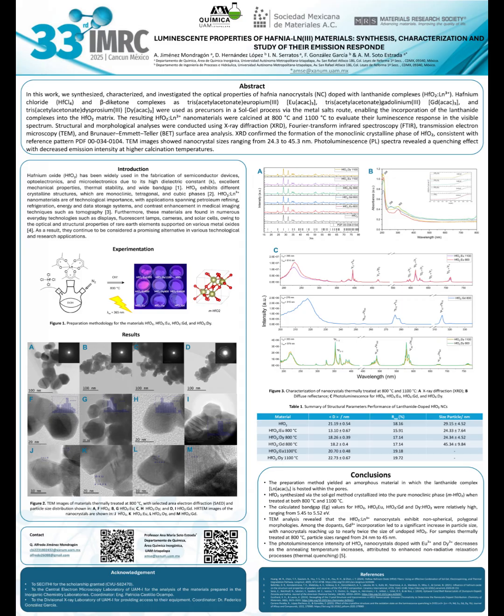As illustrated in Figure 1 of the poster, the precursors were dissolved in ethanol and mixed under a nitrogen atmosphere at 600 rpm for 2 hours. After that, ammonium hydroxide was added to catalyze the sol-gel reaction. The resulting gel was washed with deionized water, dried and thermally treated at 2 different temperatures, 800 degrees C and 1100 degrees C, to evaluate the effect of temperature on structural and optical properties.